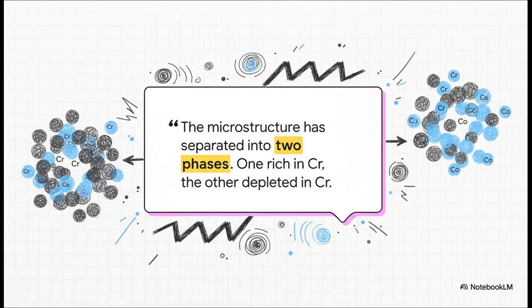And there it is, the smoking gun. The atom probe revealed that the material had separated into two completely different phases. One phase was packed with chromium, and the other was almost pure, highly magnetic cobalt. The old theory was totally wrong. The atoms weren't just moving to the edges. The entire material was actively reorganizing itself from the ground up.